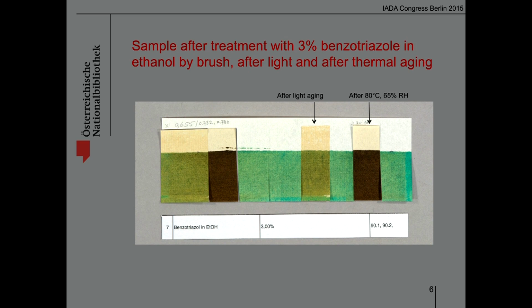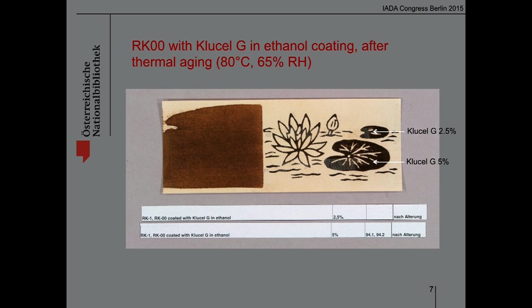Pre-coated Japanese tissue papers proved to stabilize rag paper mechanically without inducing further damage after light and after thermal aging. Homogeneous and matte films can be achieved by brushing dilute adhesives on a silicone mat. Activation of pre-coated papers with the sponge plotter system developed by Jacobi et al. reduces the risk of migration of copper ions.